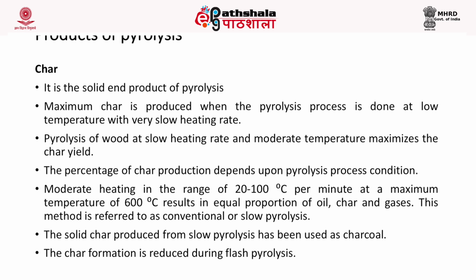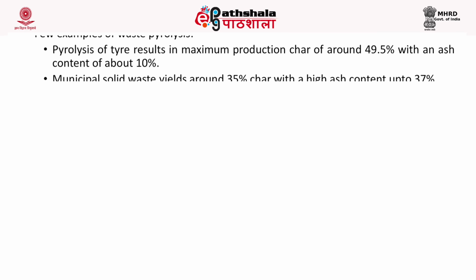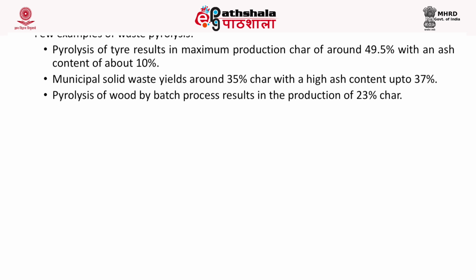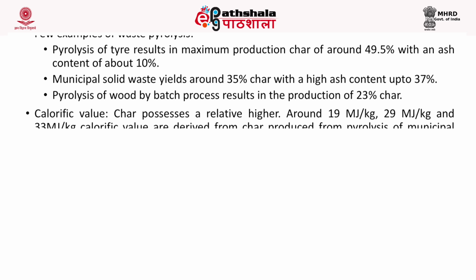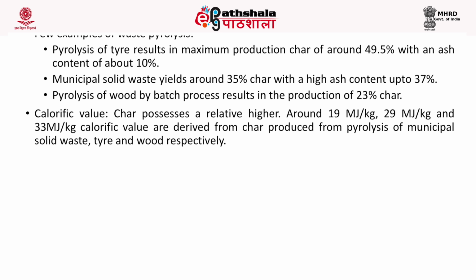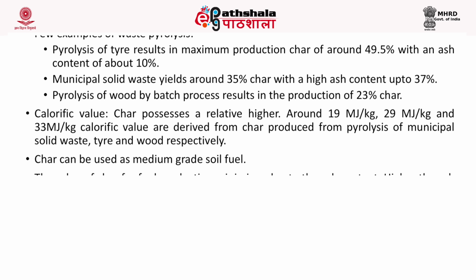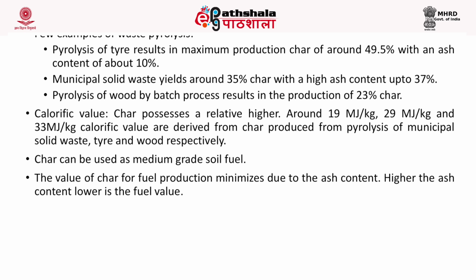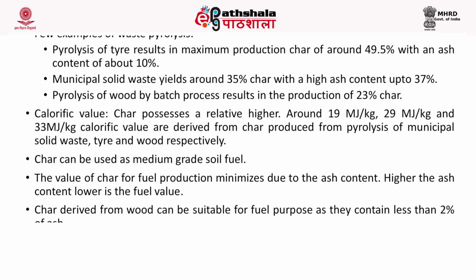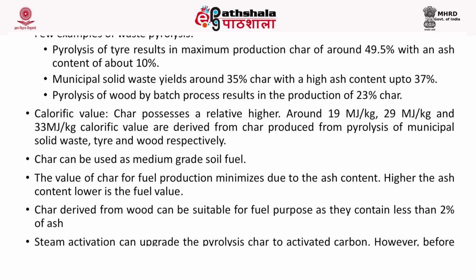Also, in flash pyrolysis, the char production gets minimized or reduced. Now, a few examples of waste pyrolysis: pyrolysis of tire results in maximum production of char of around 49.5% with an ash content of about 10%. Likewise, municipal solid waste yields 35% char and an ash of 37%, which is relatively high. Also, the pyrolysis of wood by batch process results in char production of 23%.